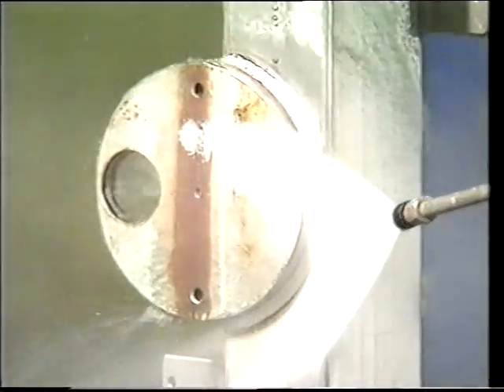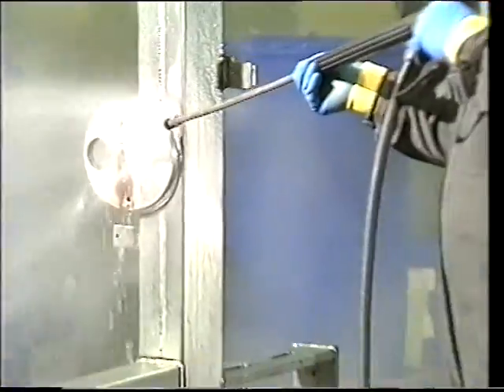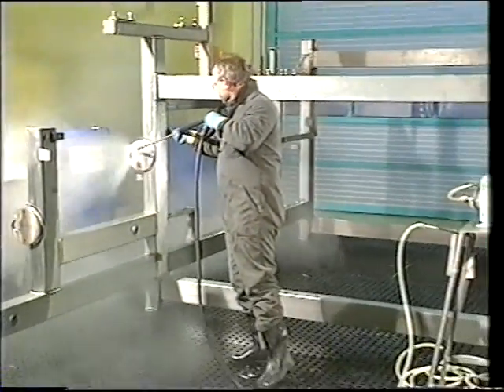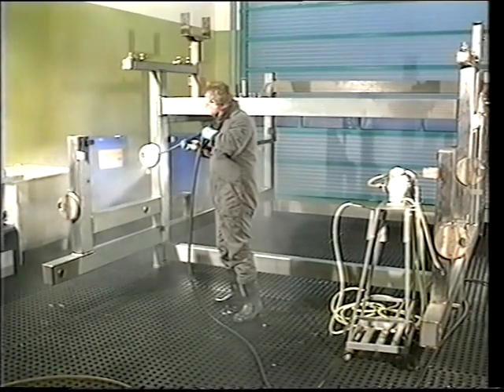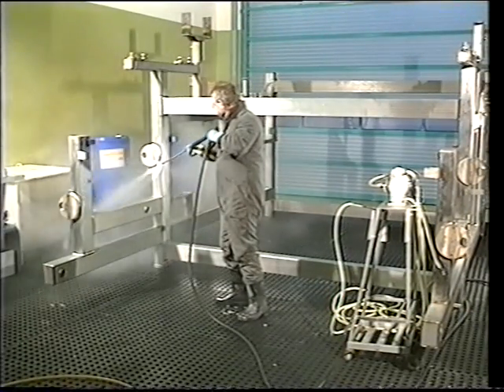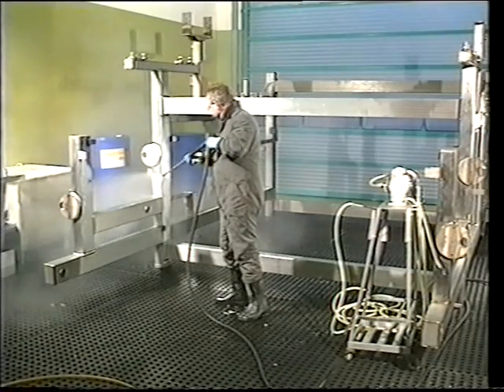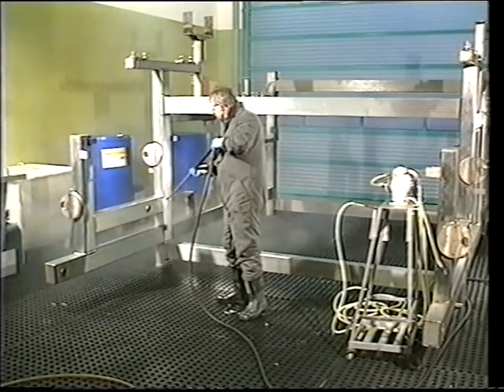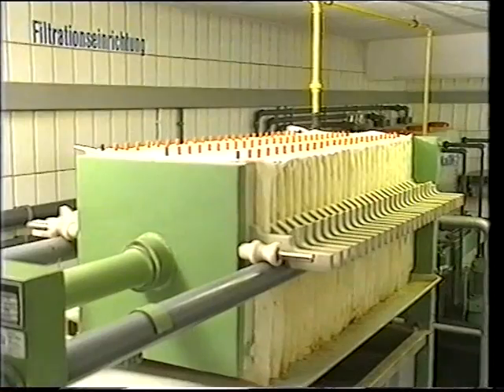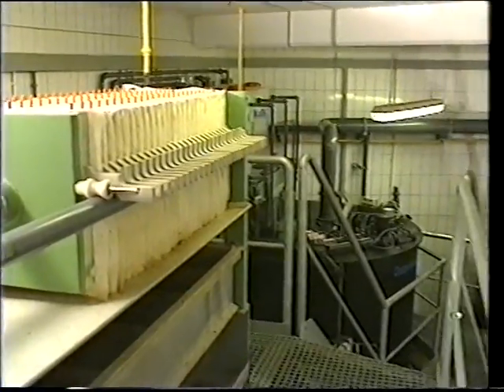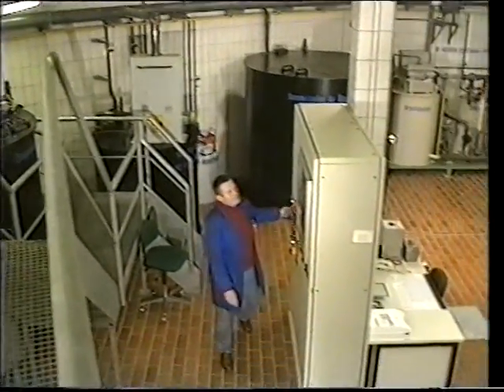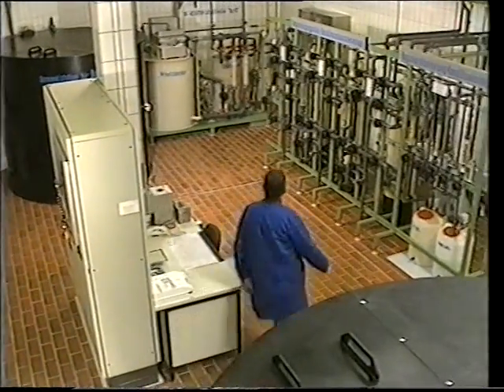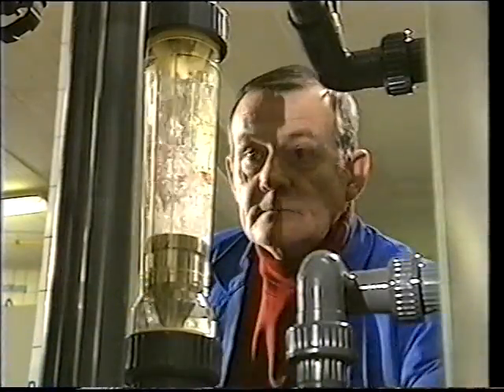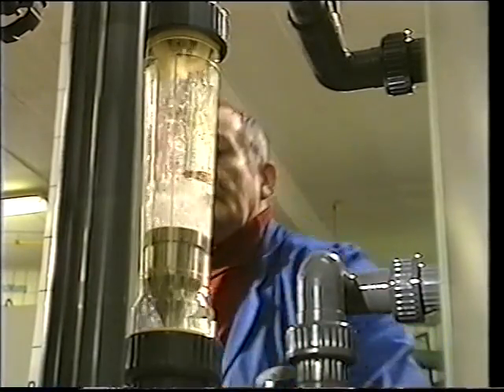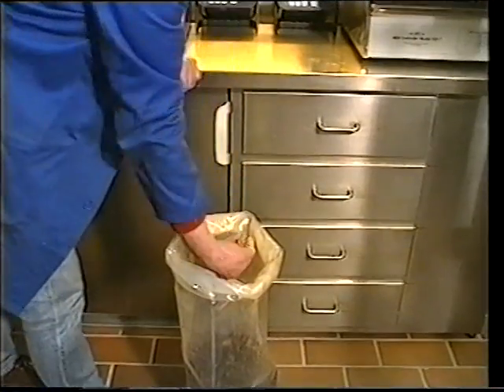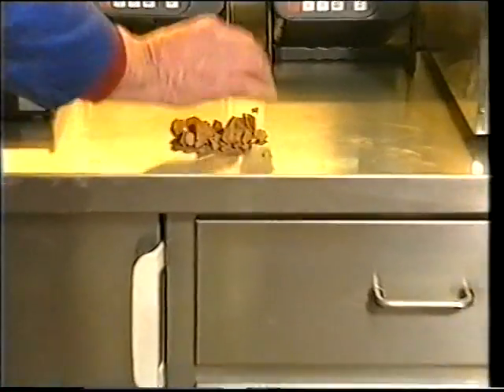Once pickling is complete, residues must be rinsed off. The best rinsing method is cold water at high pressure, at least 1,800 pounds per square inch, sprayed onto the parts from top to bottom. Metals dissolved in the rinse water, such as iron, chromium and nickel, as well as dust and other contaminants, must not be allowed to enter sewer systems. Local wastewater regulations must be observed. With additional processing, treated rinse water can be reused. That is both economical and environmentally conscious. The only waste is a hard filter cake that must be disposed of.